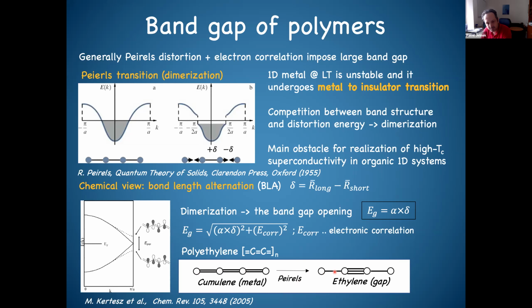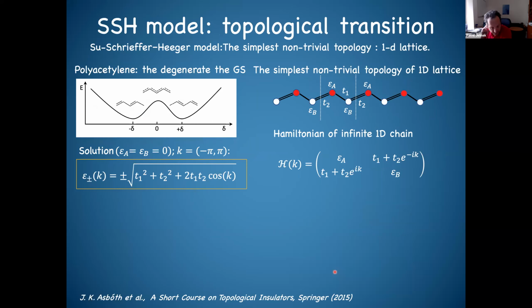So if the alternation of the bonds, like single, double, etc., is larger, then the band gap which we are opening in the system is also much larger. So the idea here is we would like to look at these systems, and one of the very famous models to start to deal with this bond length alternation is the so-called SSH model, which was actually at the origin of the discovery of these conductive polymers. There was an open question why polyacetylene can be conductive, and this is actually a very simple molecule. It's a linear chain where you alternate the bond of single and double.